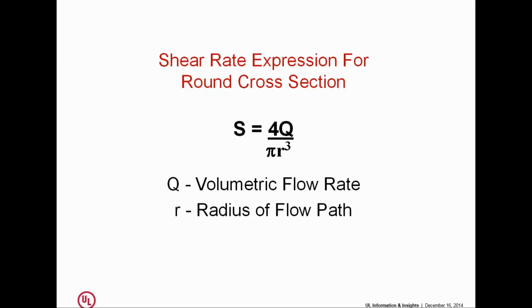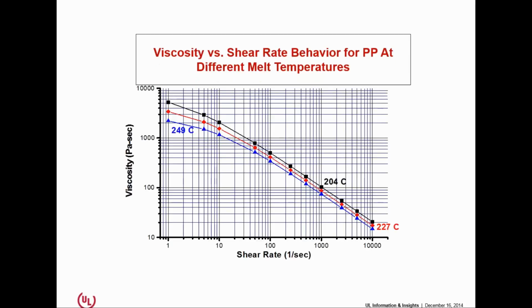And by the way, this is the equation that governs shear rate. Again, a simplified equation for a round cross-section, and a simpler equation than the one I just showed you. Notice that Q is in this equation. This is your injection speed, and R is in this equation. That is the geometry of your flow path. This is one of the reasons we get away with restrictive flow paths, because as we go to more and more restrictive flow paths, our shear rate goes up. When our shear rate goes up, as we just saw, our viscosity goes down.